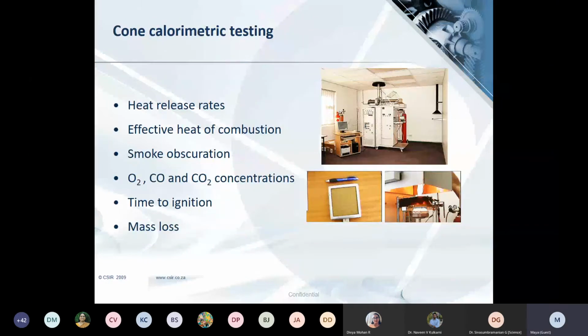So this is just a picture of the cone calorimeter and the parameters one can get from cone calorimetric testing. You can get the heat release rates, the heat of combustion, the smoke release rates, the concentrations of gases like carbon monoxide, carbon dioxide, and oxygen, how much time it takes for the sample to ignite, and mass loss. So on top, you have the picture of the cone calorimeter. Bottom left, there is the sample in the holder. And on the right, you see the sample while it's being tested in the cone.